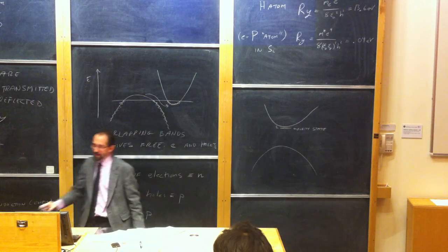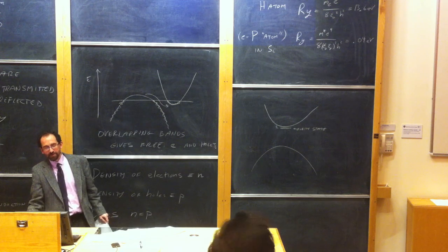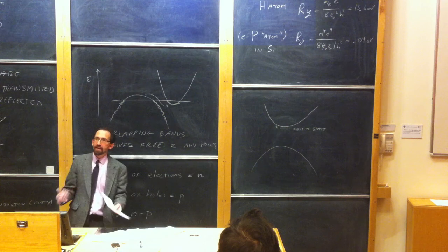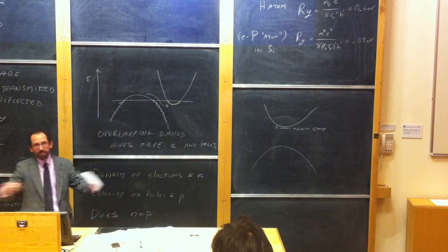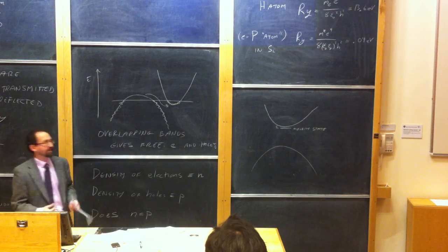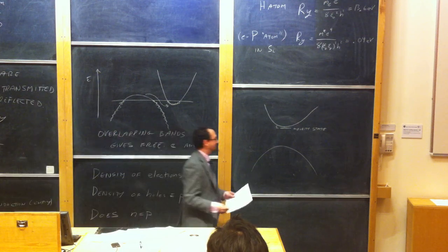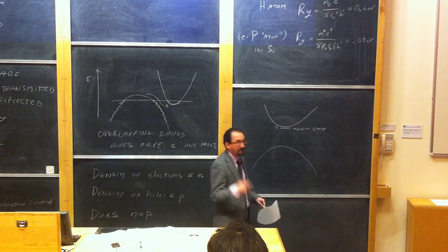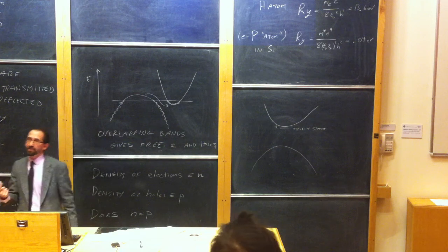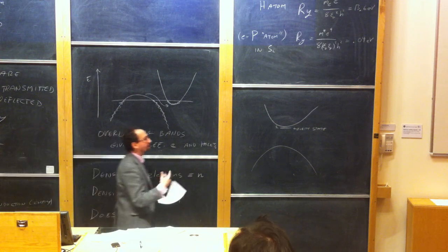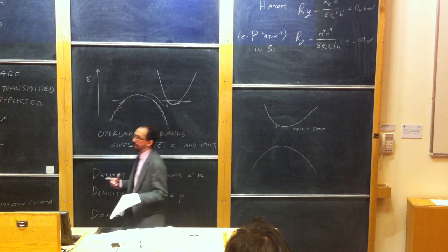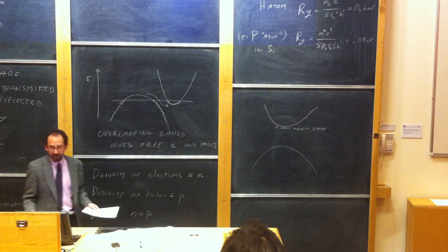And that's why I was saying that this positive phosphorus charge really doesn't do much. The electron breaks free from it at reasonable temperatures and then runs around the conduction band, and this positive charge is then just some disorder that the electron will experience where it comes nearby. At low enough temperature, the electron will get bound again to the phosphorus atom and get stuck, and you'll see the apparent number of electrons in your system will drop as the electrons get bound again to their donors.